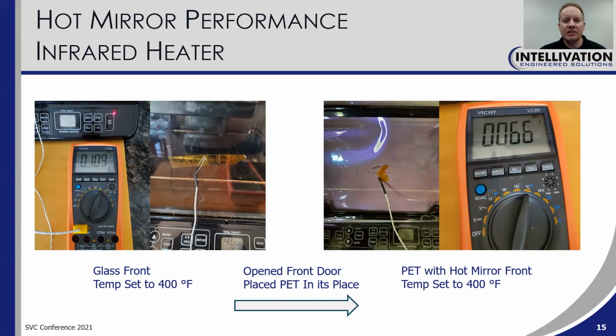For the hot mirror, we did go ahead and run a test to see kind of how it performs. So we attached a thermocouple to an oven, and on the left there was a thermocouple directly on the oven. The thermocouple reached 109 degrees Celsius. And then we also put the hot mirror coating in front of, facing the oven, and the temperature reduced to 66 degrees. So we certainly see some effectiveness of that coating in that case.